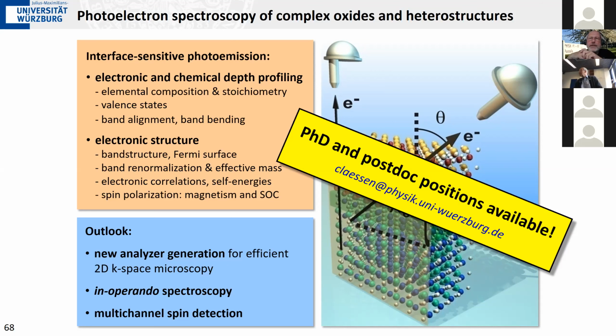Generally, it's always a little dangerous to use the X-ray absorption data, because you have two states that are playing a role here. It's the 2p from which you excite, and it's the 3d into which you excite. If you use it as a fingerprint, if you have nice reference spectra and you use it as a fingerprint, that's fine.